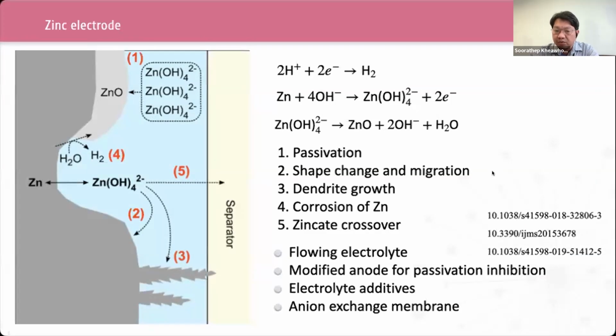Next, dendrite growth. This is a notorious issue of the zinc electrode. At high current density, especially in alkali electrolyte, or in a condition where zinc deposition is limited by mass transport, zinc tends to deposit in the form of dendrite and penetrate the separator, causing short circuit. And the next issue is corrosion of zinc. Zinc can react with water to produce hydrogen. In other words, zinc can donate electrons to water molecules instead of giving them to the external circuit and oxygen at the air electrode. This is a parasitic side reaction. Corrosion of zinc leads to losing of electrolyte and zinc without producing electricity.